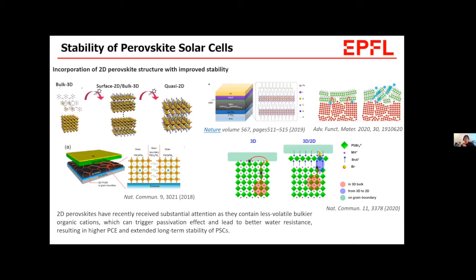Technically, there are some different approaches, but basically the most common approach is to deposit 2D perovskite on top of 3D perovskite, layer by layer, so that we can protect the underlying 3D perovskite from external stresses, as I mentioned, mostly moisture, and some metal ion migrations as well. The other approach is to incorporate the 2D perovskite in the bulk, so that the grain boundaries are filled with 2D perovskite here, for example. This is the right example that I would like to introduce.